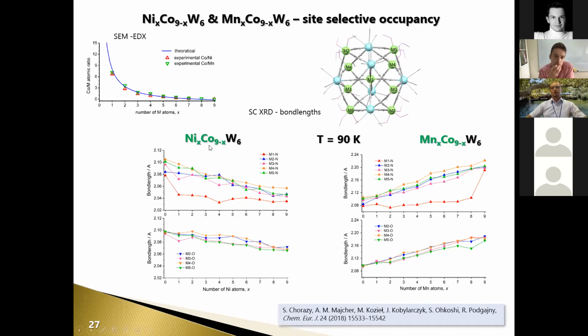So when we put in the solution even a small amount of nickel, in the crystal data we see that this metal ion is located here. This is based on the data for bimetallic nickel tungsten, cobalt tungsten, and manganese tungsten. Again, in the manganese cobalt series, we see the preferential occupation of the central site with the smaller metal ion. With the external site, we have rather the statistical occupation according to the composition of solution.